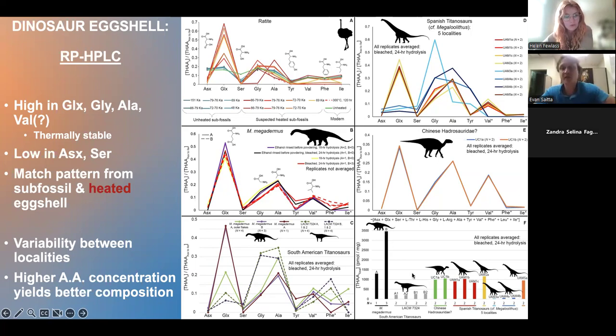But for example, gray, light blue and dark blue, those are the dinosaurs that did not give very good results. The dashed lines are the gray. So what we see is that once you get above 500 or 1,000, you are able to detect a pretty decent profile, which matches what you would expect from a diagenetically altered bird eggshell.